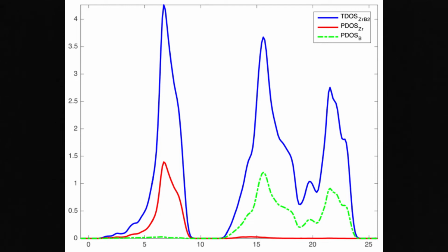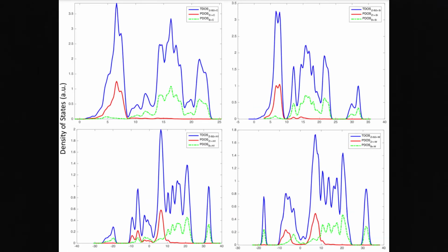The DOS for the covalently bonding impurities closely overlaps with the pure crystal, but with more dominating states, likely from the projected orbitals of silicon and carbon at higher energy. The potential bonding interaction between the covalent nature of zirconium diboride and both silicon and carbon is noticeable in the overlap, which is not the same for the metallic impurities. Both carbon and silicon have an almost similar graph but with different values.